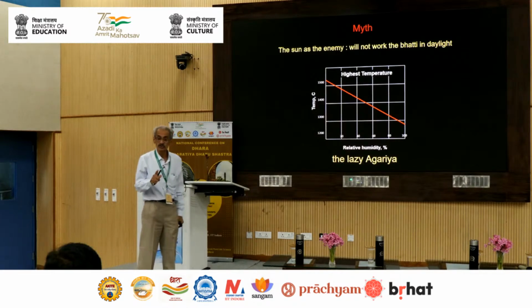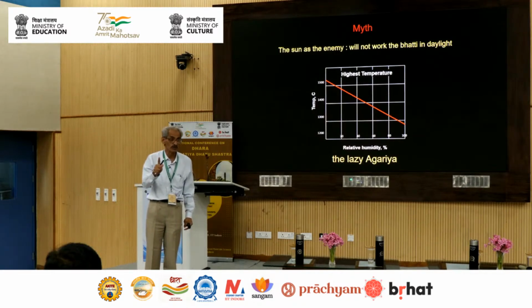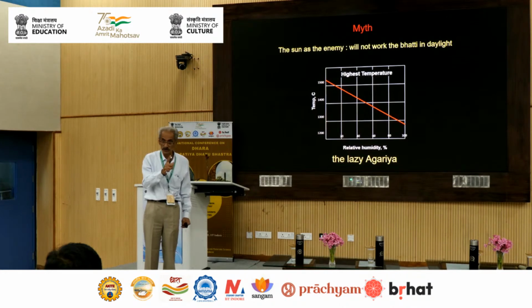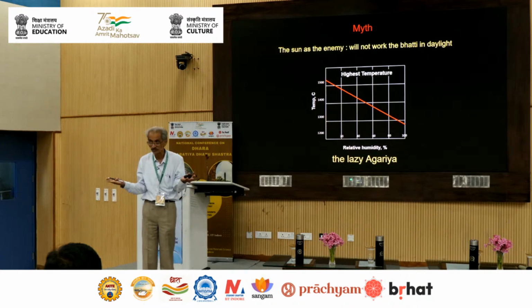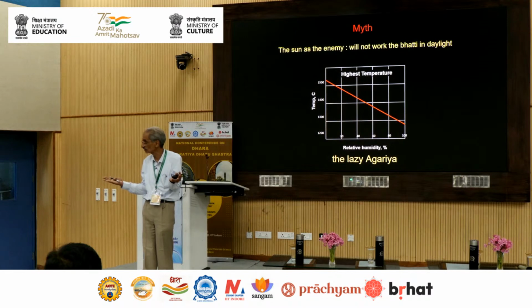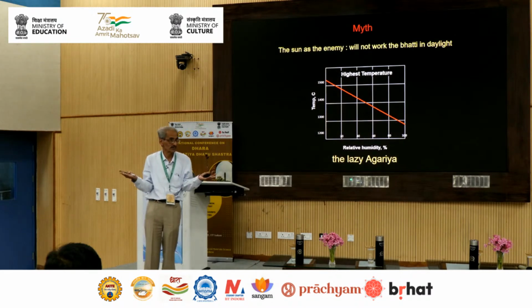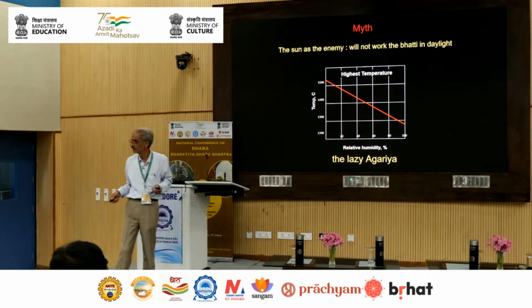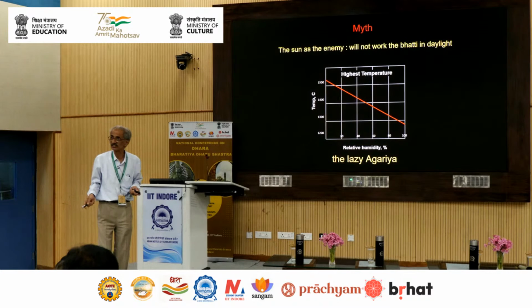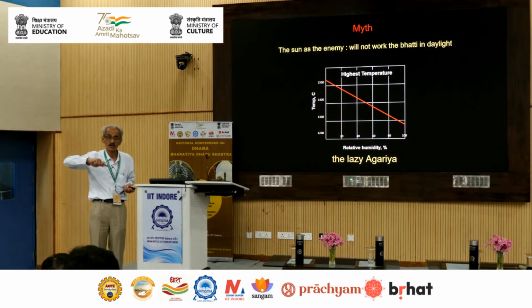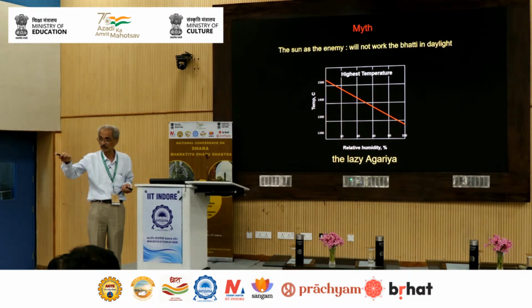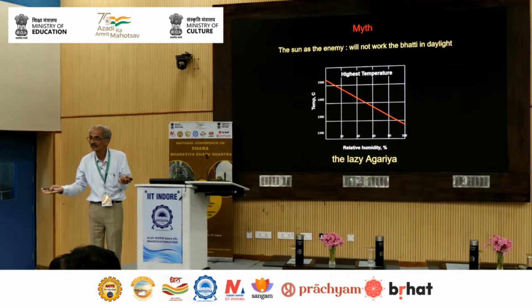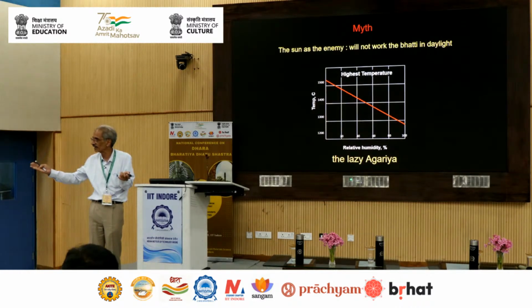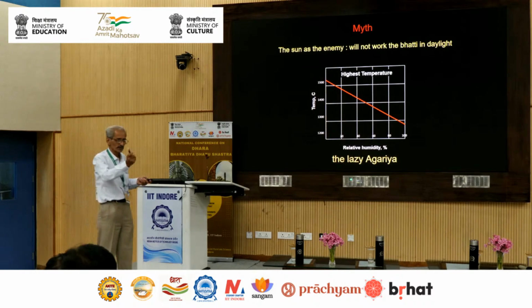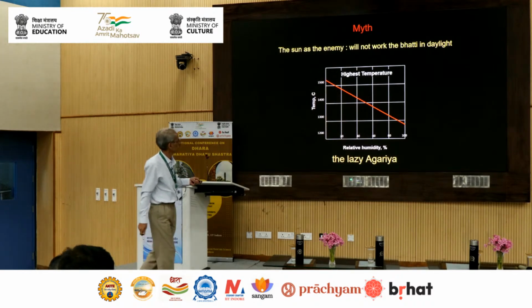And that is why also they work very well in winter. Though winter temperature is lower, the humidity is absolutely low, 20%, 25%, even less than that. Whereas in summer, it is 85%, and the temperature is high, absolute humidity is very high. So they make their iron in winter, and it works with the farming activity, because in summer when they do the farming, these fellows are free to do the smithy operation, repair the tools, and so on. So it matches with the farming community.